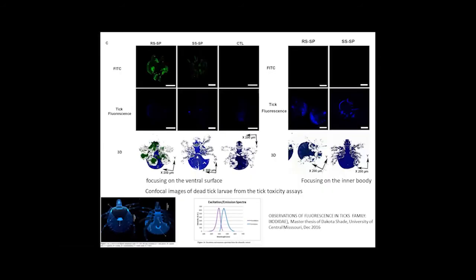Fluorescent confocal microscopy was also employed to directly observe the adhesion behavior of nanospinosad, which are labeled with a green fluorescing probe. While focusing on the ventral surface of a tick, which means we're focusing on the outer surface of the tick, green fluorescence from both the rough and smooth spinosad can be clearly observed here, indicating that nanospinosad were attached on the tick body surface. The confocal image of rough spinosad shows much stronger green fluorescence than that of smooth ones, stressing a higher adhesion amount. The weak blue fluorescence can be attributed to the tick autofluorescence, which has been reported before.